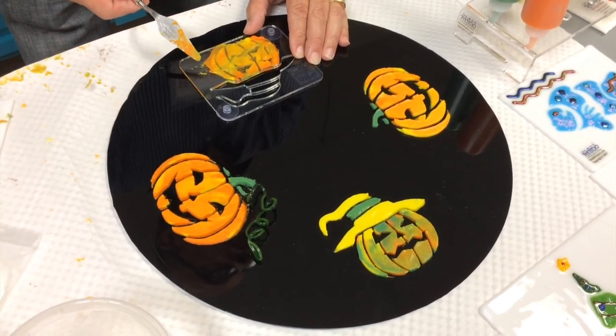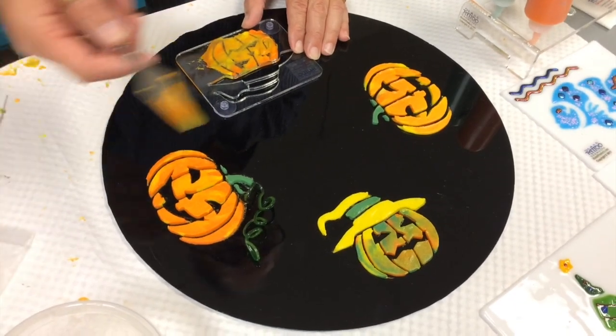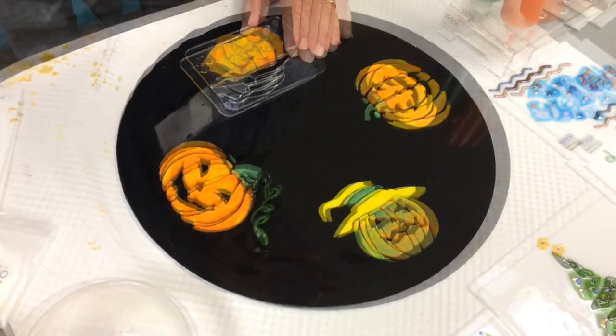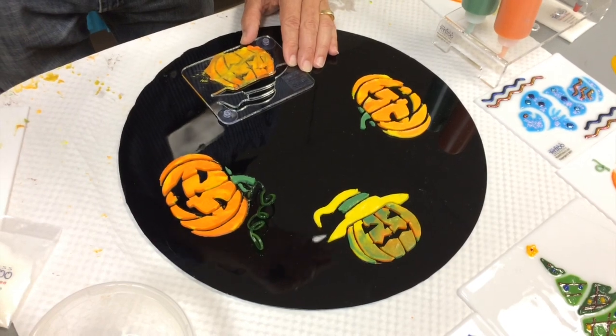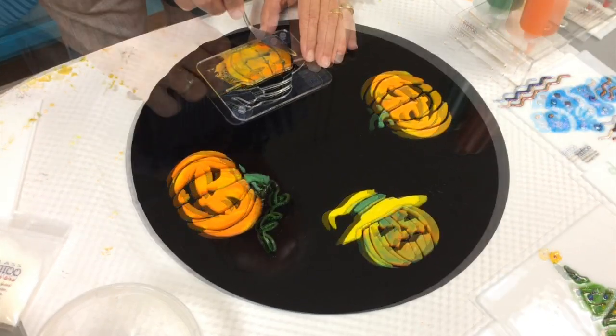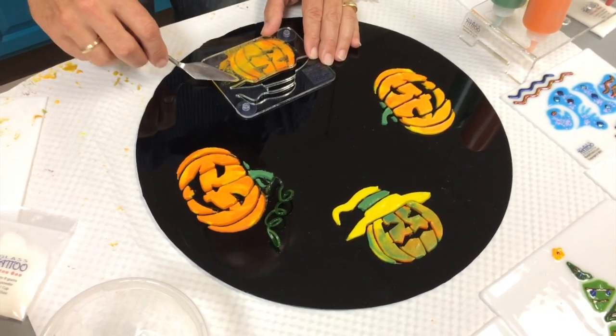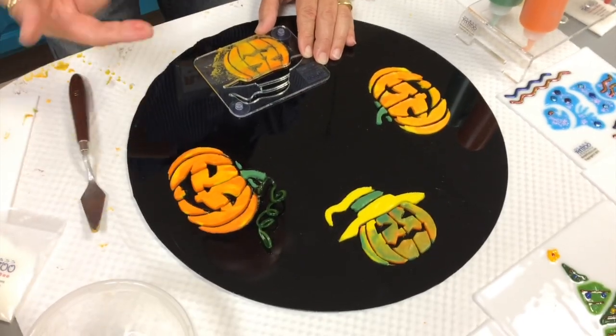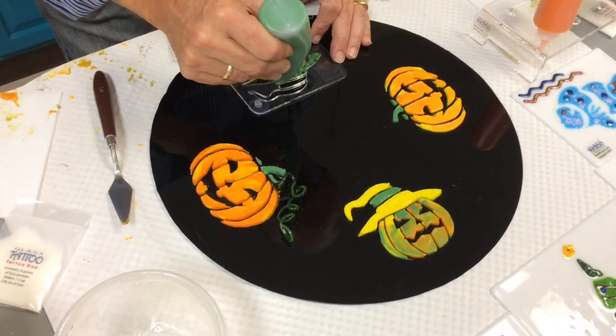This is an eighth-of-an-inch thick stencil, so you're going to be left with a sixteenth of an inch of powdered glass, which is how you get those really nice deep colors. If you only had really thin stencils — a thirty-second of an inch — you don't have a sixty-fourth of powder, and it's not enough to get the deep colors. You keep the knife fairly flat, just a little bit of an angle, so you're getting the top of that stencil nice and flat. Now we're going to put the hat on.